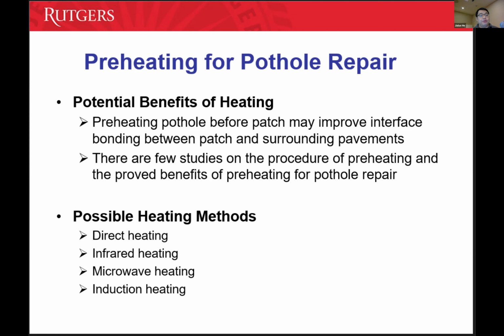Induction heating also has been used for self-heating. In this case, you create a magnetic field, and if you make the asphalt partially conductive by adding steel powder or steel fiber, you are able to generate current and heat. So it requires the repair material to be conductive. It cannot be used for regular asphalt mix without any conductive material like steel powder or other materials. So we are using infrared heating to check for this project.